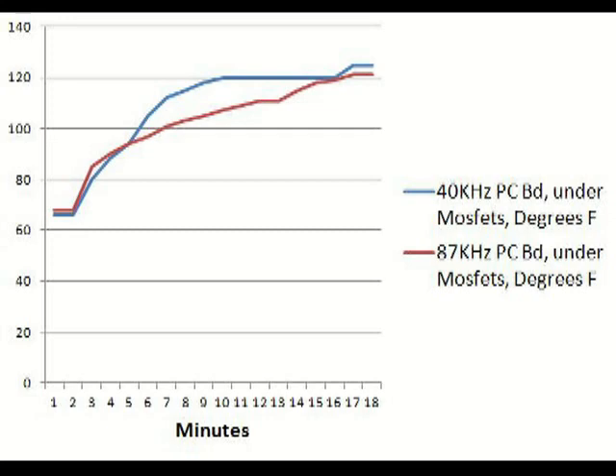Temperature of the PC board under the MOSFETs. The bottom of the PC board heated more slowly during the middle of the 87 kilohertz test than the 40 kilohertz test, but ended up at about the same temperature as for the 40 kilohertz run. Again, the temperatures had almost stabilized by the end. I forgot to measure the chokes this time, but I think the PC board under the MOSFETs temperature measurement is related to the chokes because of heat transfer from them to the heavy PC board traces.